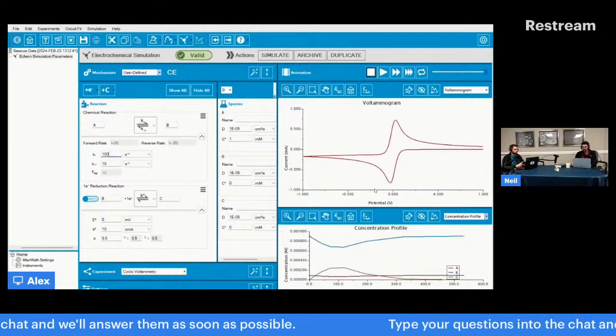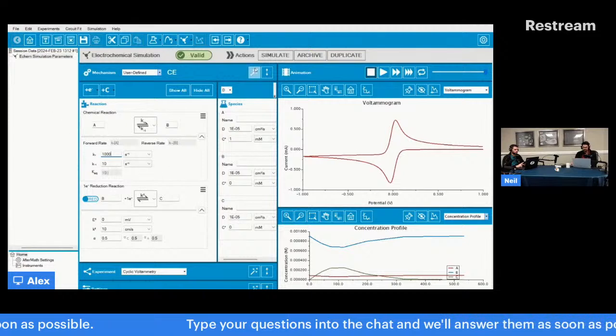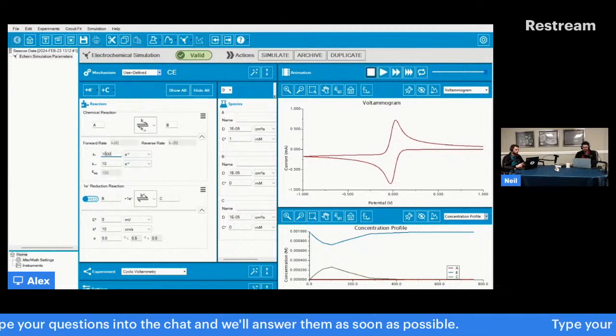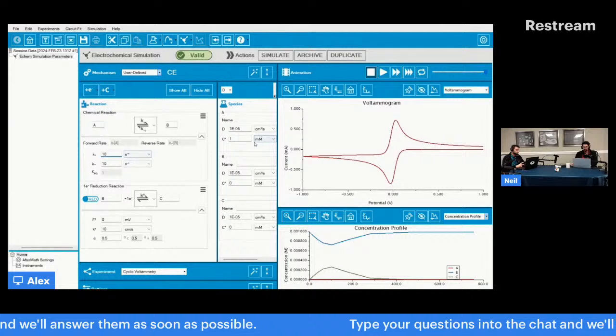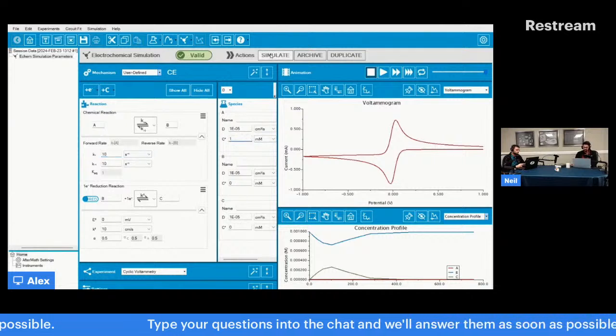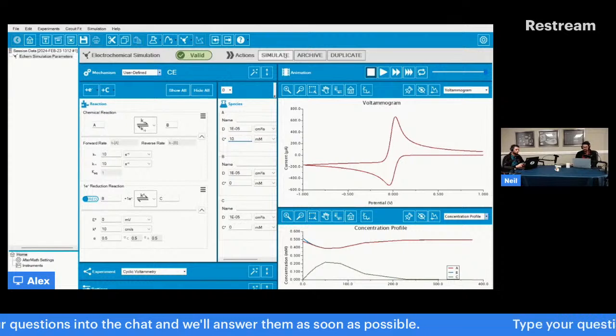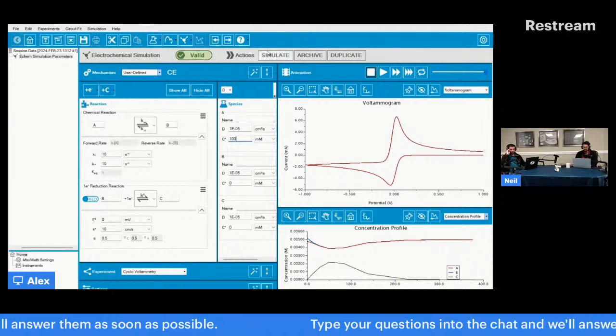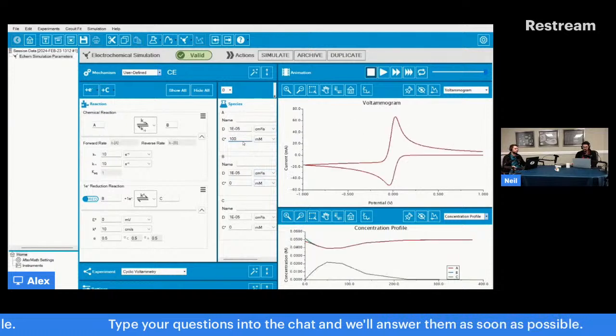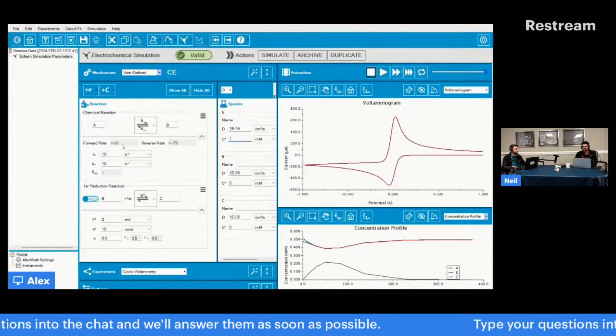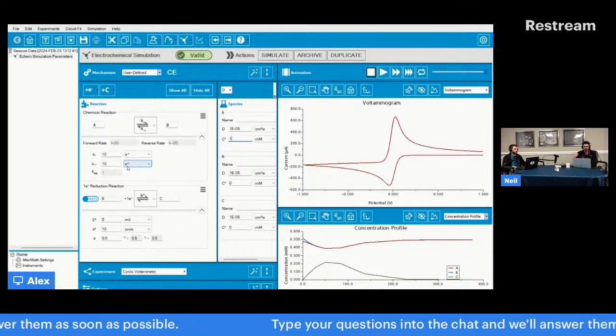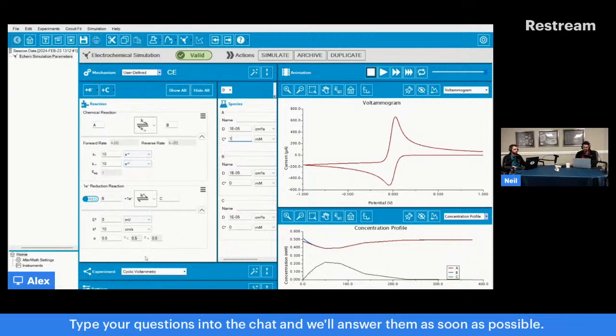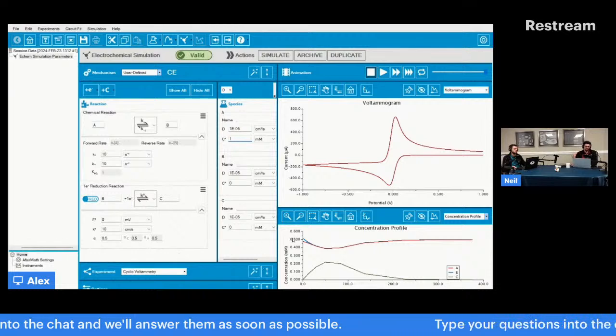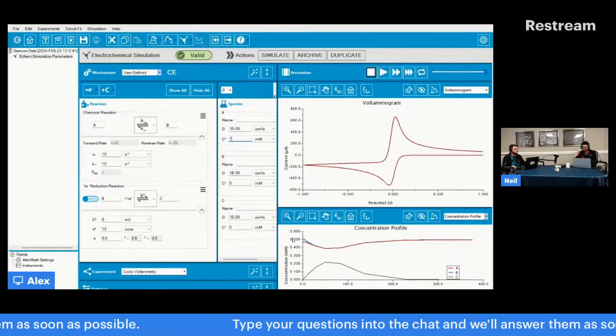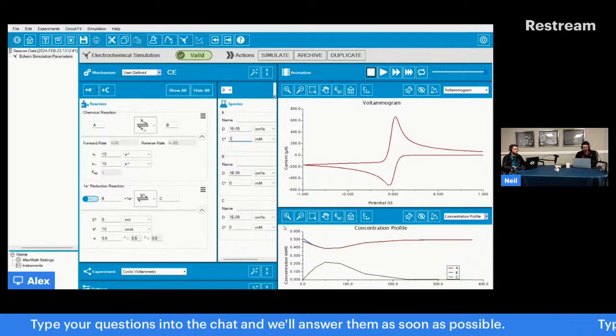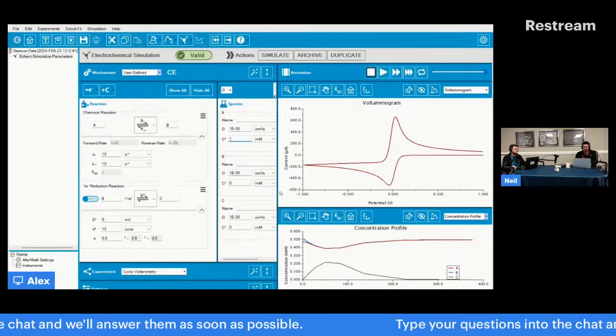And when they do that, you'll end up getting these kinds of different results as you change the acid, not concentration, but activity. Additionally, you can also adjust the concentration of the acid that you're using. If I have like 10 millimolar, you will mostly not see a major difference in how it'll look or behave. But usually changing the acid, or how quickly this reaction occurs, will affect how this reaction will occur. So this is all to say that using this simulation software is probably one of the best ways